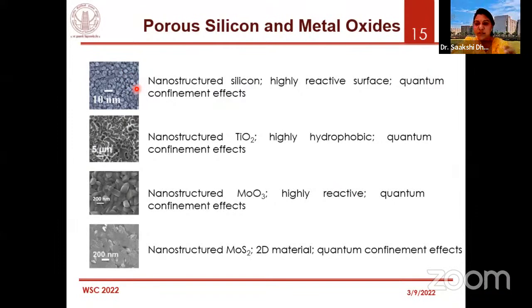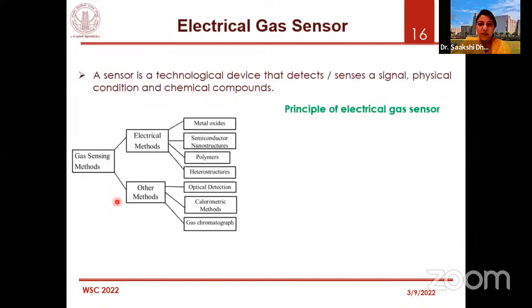It's a silicon material with nanostructured pores. So we are left with nanocrystallites between the pores. These show quantum confinement effects. And so we are able to use this even standalone as a sensor. And if you club it with titanium dioxide or molybdenum trioxide or even molybdenum disulfide, which is a 2D material, we are able to see great results.